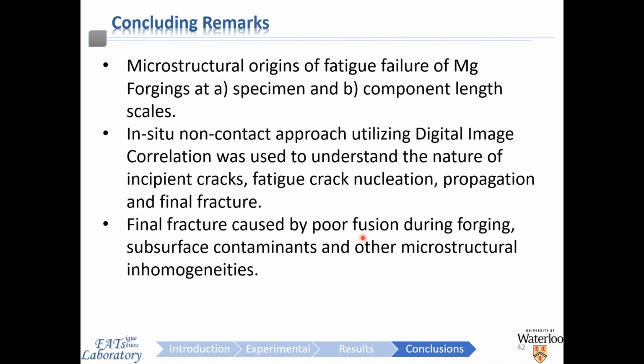The microstructural origins of premature fatigue failures were investigated on a variety of forged magnesium components, both at the specimen level and the component level. A novel in situ non-contact approach using the digital image correlation technique was used as a screening test to establish the presence of these intrinsic defects and reliably predict their effect on the final fracture behavior in an accelerated manner compared to conventional methods such as strain gauges. The fracture behavior was deterministically traced back to a combination of various effects, all having a microstructural origin, including poor fusion during forging, entrainment of contaminants subsurface, as well as other inhomogeneities in the thermomechanical processing history.